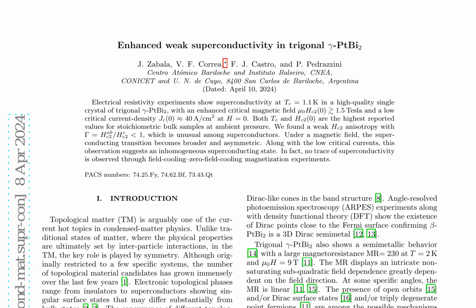The research paper presents an enhanced weak superconductivity in trigonal gamma PtBi2, a unique material with topological properties. Electrical resistivity experiments reveal superconductivity at Tc equals 1.1 K, accompanied by an enhanced critical magnetic field Hc2(0) of 1.5 Tesla and a low critical current density Jc(0) of 40 A per square centimeter.